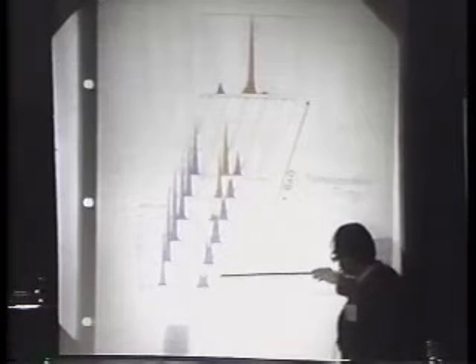If you don't substitute the lanthanum by, say, barium or strontium, by an alkaline earth ion, it's orthorhombic. And when you substitute, it gets tetragonal, as exemplified here by this X-ray data as a function of the barium content. So it's split here, and smoothly you see only one line. Here it's tetragonal, and it's around here at this concentration where you have the optimum transition temperature observed in these layer compounds. And I showed you our data for the orthorhombic case, in between number 2 and 3 for optimum transition temperature in these layer compounds.